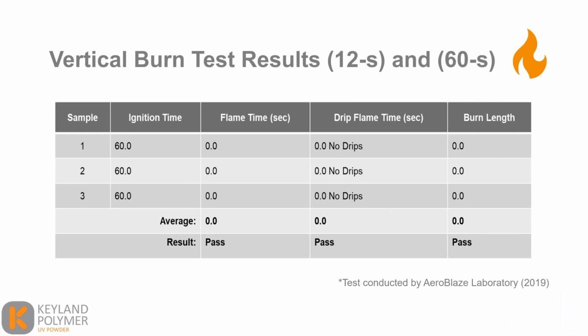So we've done some third-party testing specifically for the aerospace industry. The results of this testing are the vertical burn. These were conducted by AeroBlaze in Fort Worth, Texas, and this is the 12 and 60-second burn testing. The substrate with the powder coat is exposed to a 1500 degree flame for 60 seconds. And then the amount of flame, drip of the flame, and burn length are all measured. And as you can see, we passed these flame tests.